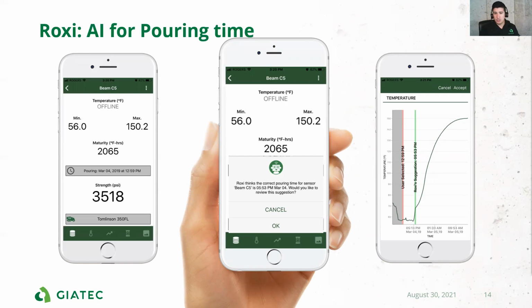Why is that? If we tell the sensor that the concrete was placed at 10 a.m., but really the concrete was only placed at 3 p.m., we have a 5-hour gap there. We have 5 hours in which the system is calculating strength out of nothing because there was nothing touching the sensor. However, if we have an intelligent system in place that tells us, hey, the suggested pouring time is not 10 a.m., it's 3 p.m., because you had a large pour, we can have a more precise strength prediction. We can have a more precise and more conservative approach towards our concrete control.